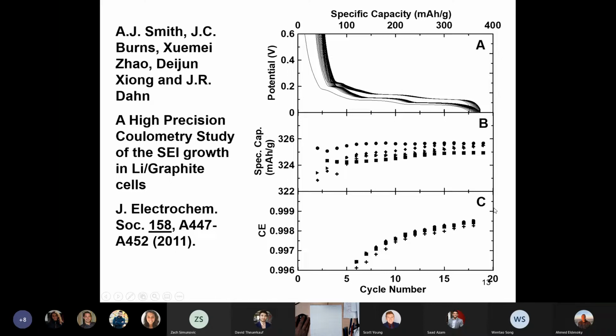And then panel C plots the Coulombic efficiency. This is the discharge capacity. Excuse me. In this case, it's the lithiation capacity. No, I've got it wrong. It's, in this case, the delithiation capacity divided by the lithiation capacity. So it's the capacity measured when you remove the lithium divided by the capacity when you add the lithium again. And you can see that that's less than 1. Coulombic efficiency is less than 1, so it means the charge that you transfer to the electrode is always greater in the lithiation step than the delithiation step. And that's because lithium is being used and lost in the growth of the solid electrolyte interface. And the Coulombic efficiency gets closer and closer to 1 because the rate of thickness increase of the SEI gets smaller and smaller.